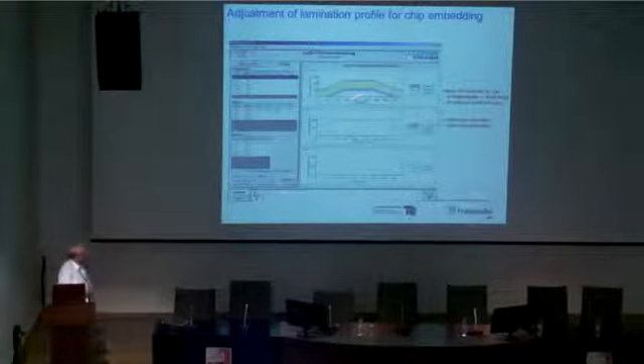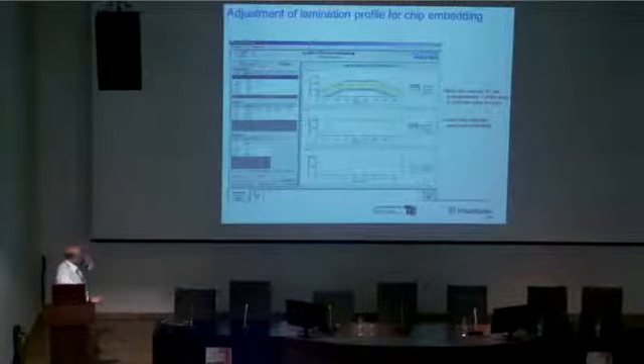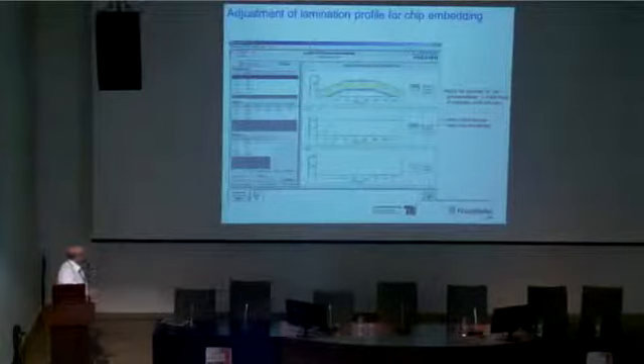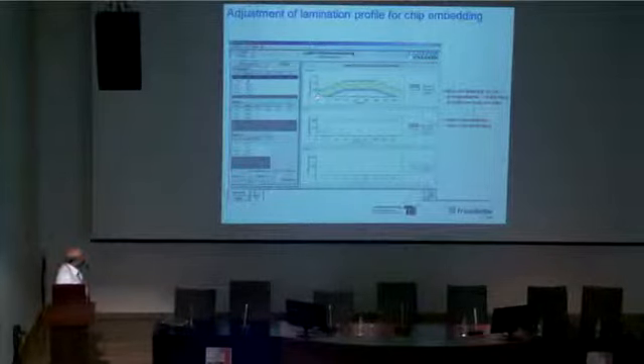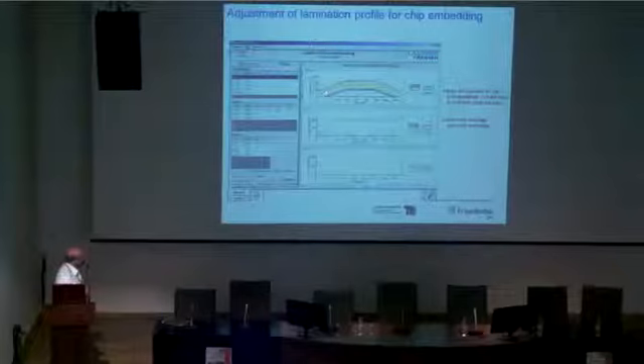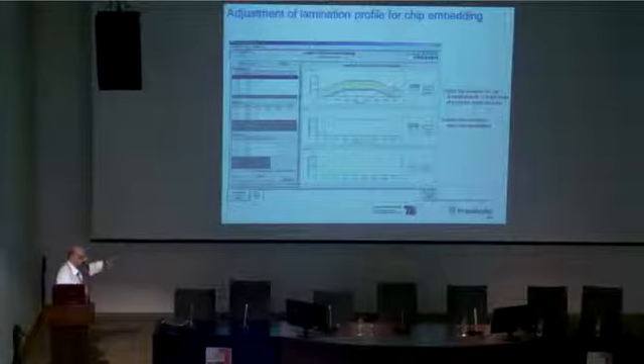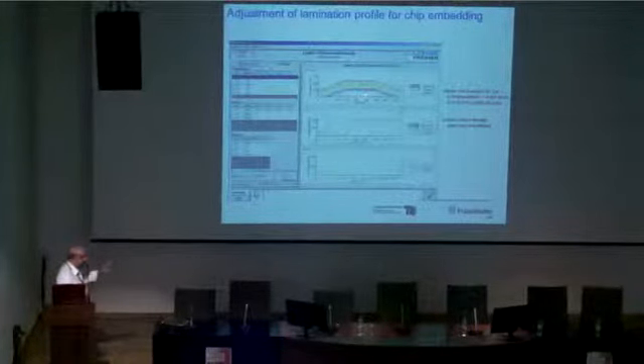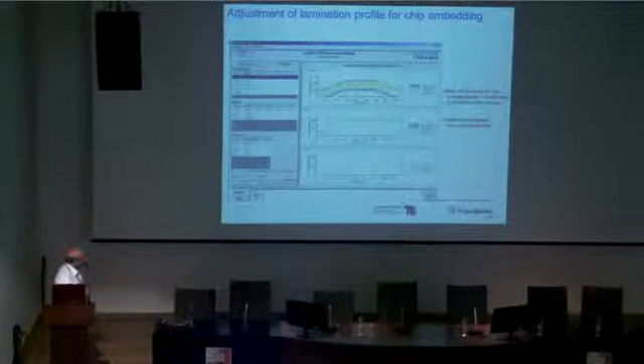So this is a typical PCB lamination process. You apply a temperature profile, and also you have to apply pressure. The heating profile is very common for the PCB. You heat up to 180 degrees Celsius, where the final curing takes place and the polymer is fully polymerized. So it is, let's say, C stage. And then you have a cooling profile.